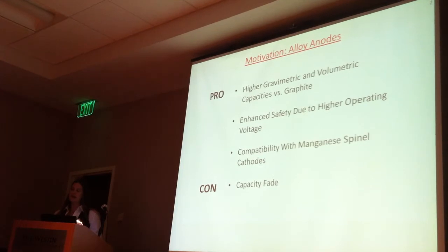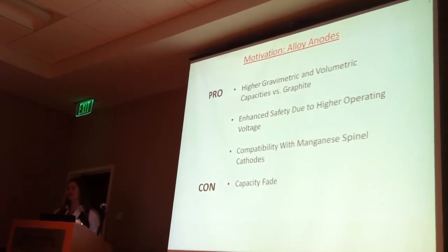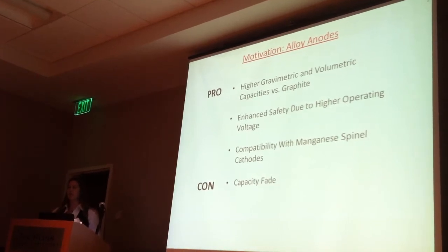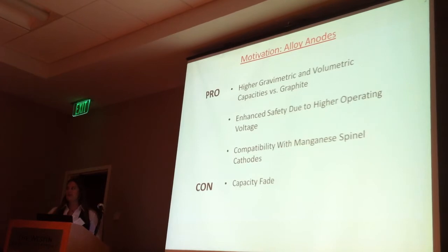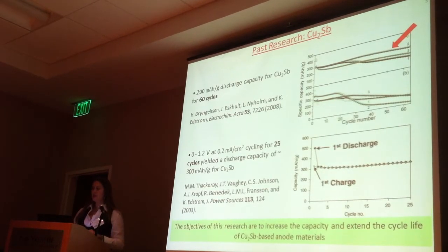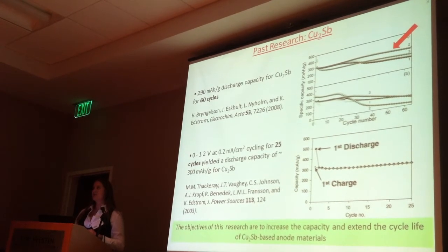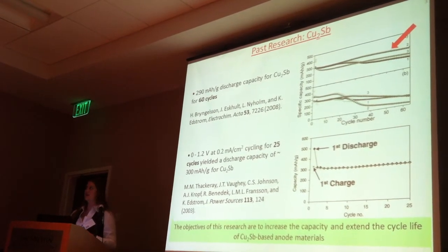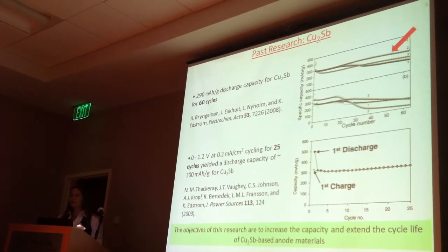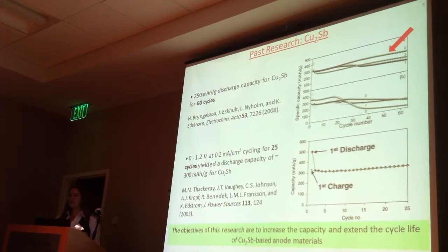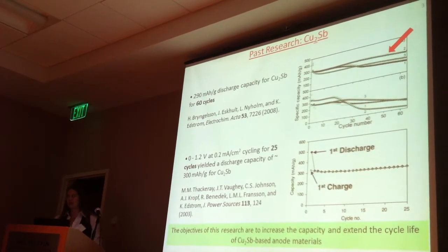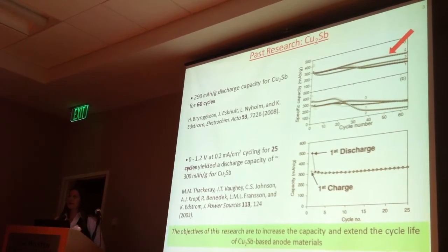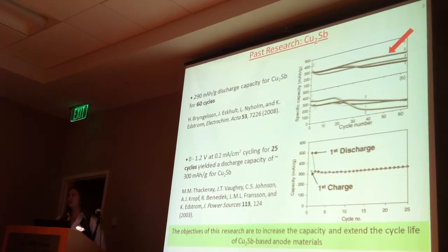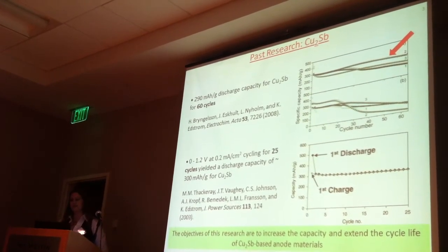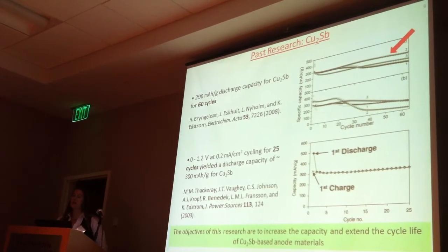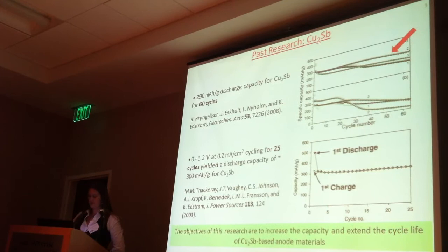The one problem is that they suffer from capacity fade during cycling. So we wanted to figure out a solution to the problem of capacity fade. So we went and looked through the literature for alloy anode materials that we might be able to start with. We decided to choose the copper antimony alloy, Cu2Sb. It's been studied quite a lot, but we haven't really seen much above 60 cycles of stable capacity life in the literature, and the discharge capacity of around 300 milliamp hours per gram. So we thought that would be a good starting point and decided to try to extend that cycle life and maybe see if we could get an improvement in performance in terms of capacity.